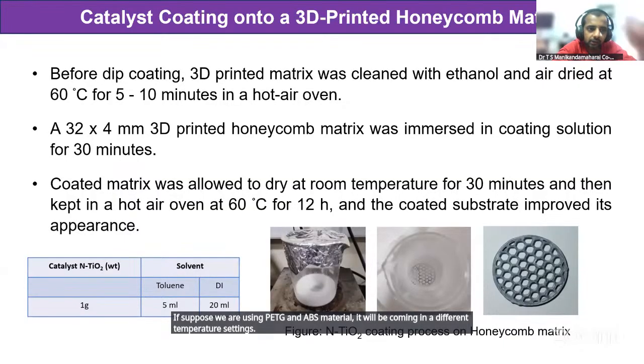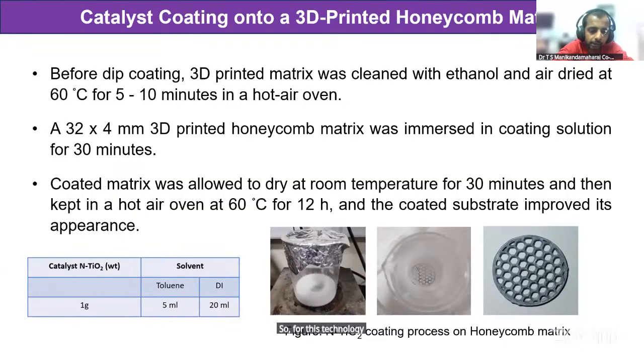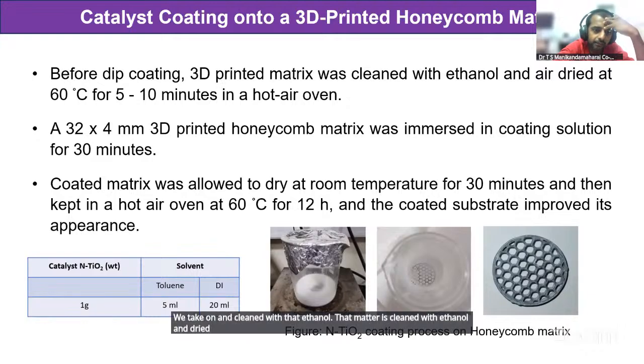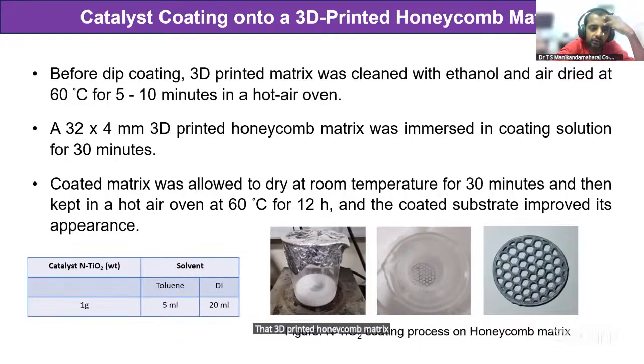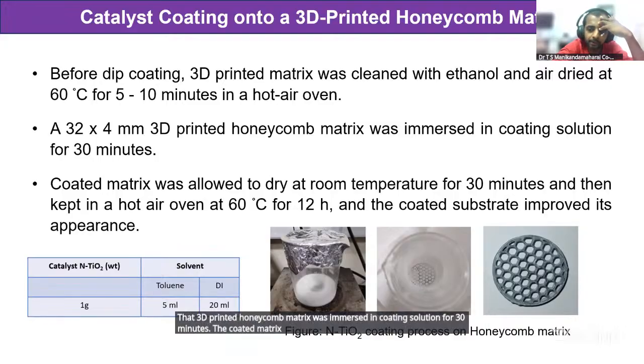So for this technology, the printed substrate is taken and cleaned with ethanol. That matter is cleaned with ethanol and dried at 60 degrees Celsius for 5 to 10 minutes in a hot oven. The 3D printed honeycomb matrix was immersed in coating solution for 30 minutes. The coated matrix was allowed to dry at room temperature for 30 minutes and then kept in a hot oven at 60 degrees Celsius for 12 hours.